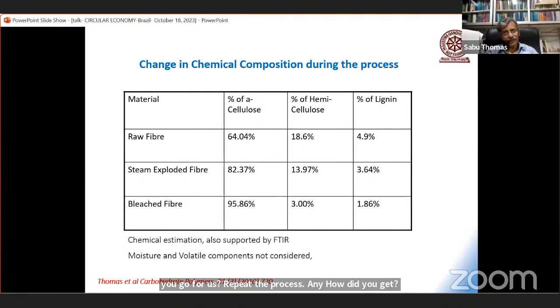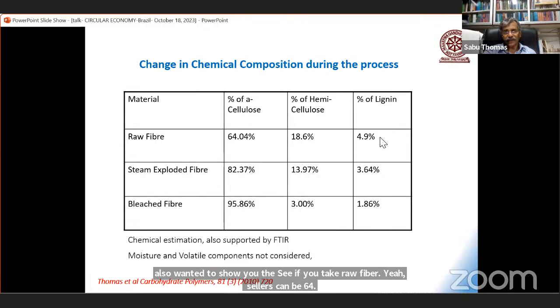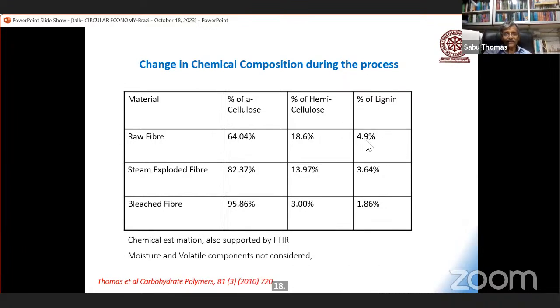I also want to show you the enrichment process. If you take raw fiber, the cellulose content is 64%. Hemicellulose is around 18%. Lignin is 4%. But after the steam explosion process, you see the amount of cellulose has gone up. After bleaching and acid hydrolysis, you get almost 95%. You can increase to 99% by repeatedly doing lots of bleaching. You can reduce non-cellulose content and get a rich content of cellulose.